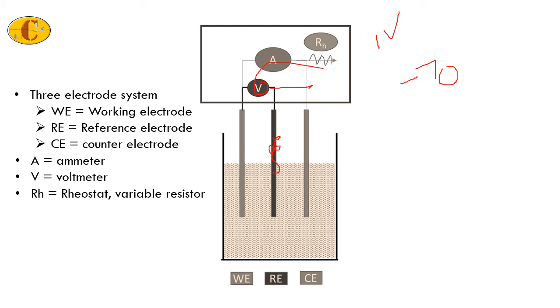These elements have their own electrode potentials, and so you essentially have a galvanic coupling between the working and counter electrode. So the potential that you measure in the voltmeter is not the standard potential of the working electrode; it is the difference between the potentials of these two electrodes. Hence, the potential that we measure here is going to be completely different than the standard value.